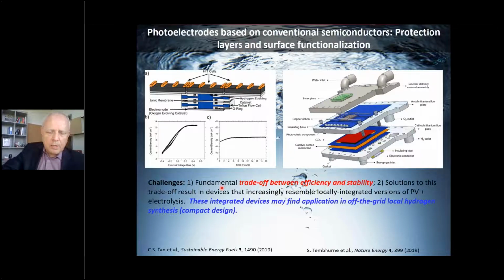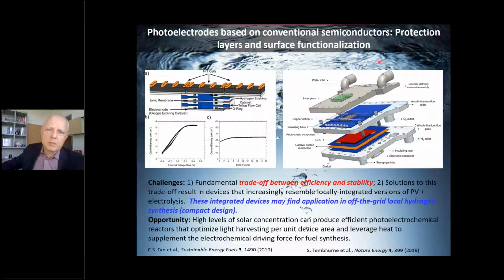But I think another exciting direction is to combine conventional semiconductors with catalysts in devices that are designed for use with solar concentration. High levels of solar concentration allow efficient photoelectrochemical reactors to operate by optimizing light harvesting per unit device area. They also leverage the heat that is generated and has to be removed from these devices through the flow of water through them, to accelerate the kinetics of the electrochemical transformation of water to oxygen and hydrogen gaseous products. So I view this as an important additional part of the ultimate technology implementation of conventional semiconductors in the photoelectrochemistry field in efficient devices.